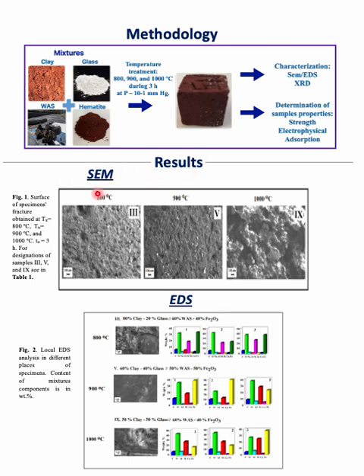The results of SEM show that the specimens have a porous structure. The porosity decreases when the temperature treatment increases, and also when the content of clay in the mixture increases. But when the temperature treatment increases up to 1000 degrees Celsius, the porosity increases significantly. This is due to the intense release of water, carbon oxide, and carbon dioxide vapors.